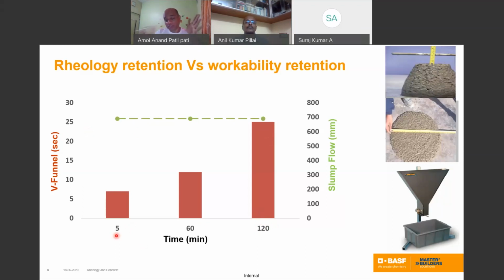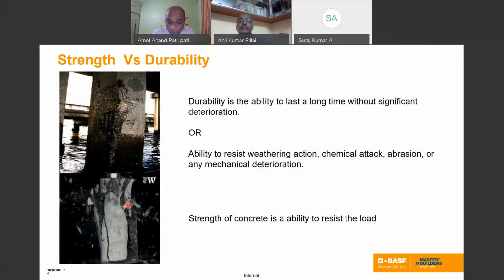Now compare the same concrete at 5 minutes and at 120 minutes. Your workability window almost remains the same. There is no deviation in the workability in terms of slump flow. But the viscosity of the concrete changes: 7 seconds at 5 minutes versus 25 seconds at 120 minutes. And that impacts your pumping operations. Now understand, this is an implication of thixotropy in the concrete. I will explain it in the easiest way. Okay, this is our understanding about rheology retention versus workability retention.